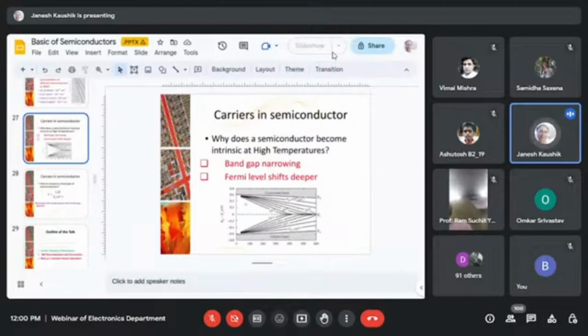So the crystal structure and energies are disturbed, so the band gap narrows, and the Fermi level, if it is doped, depending upon how much concentration there is, is shifted towards the middle. So every semiconductor becomes intrinsic. However, it becomes useless also. But wide band gap material can work at higher temperature, because their intrinsic carrier concentration is negligible to start with, so to make it appreciable we need a much higher temperature. So they are useful in high temperature applications.